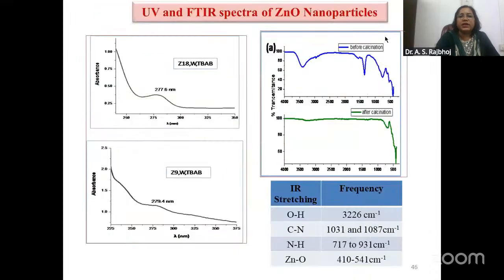You can see here the characterization we are using is UV and IR. What we are showing here is for zinc, which shows absorbance at near about 277. Then for the zinc nanoparticles, you can see OH and NH are also found because some impurity is there. For the zinc oxide nanomaterials, you can see the frequency is much lower, like 410 to 541. A sharp peak is observed here, which indicates that the nanomaterials have been formed.